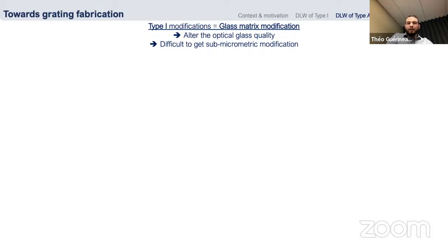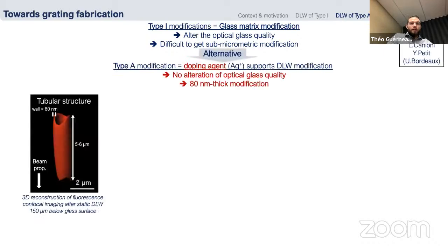The type 1 modification is interesting when we want to generate a waveguide, but it does alter the optical glass quality, and it's kind of difficult to reach sub-micrometric modification for some other kind of optical component, for instance. So one alternative that has been developed mostly in Bordeaux is the type A modification, the type Argentum. When we dope our glasses with silver and perform the direct laser writing test, the modifications are only supported by the doping element. So there is no alteration of the optical glass quality, and the modification can reach a thickness of about 80 nanometer.